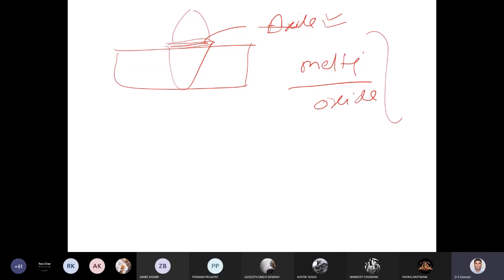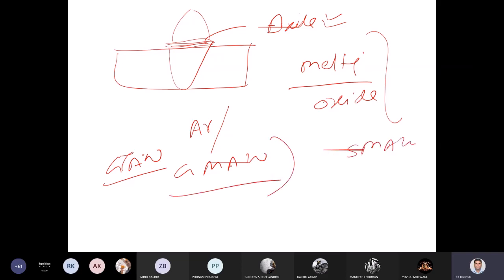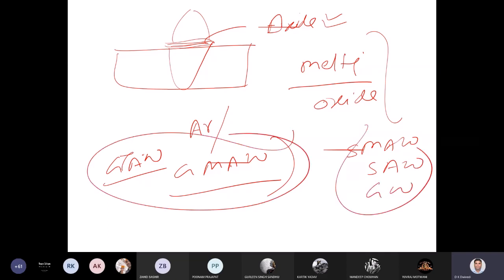So because of the formation of certain oxides with metals like aluminium, magnesium, chromium, stainless steels, titanium, they need more effective protection, and that is why they are frequently welded with good protection based welding processes like GTAW, gas tungsten arc welding, or GMAW, gas metal arc welding. They are not welded by shielded metal arc welding or submerged arc welding or gas welding. This is the main reason, because when we use these two processes, we use argon, we use helium, which helps to provide very good protection so that these refractory oxides are not formed.